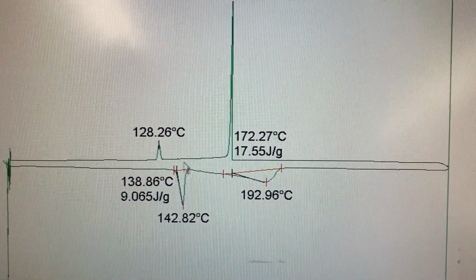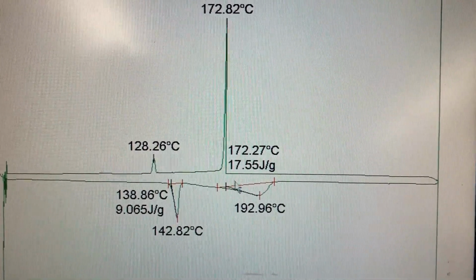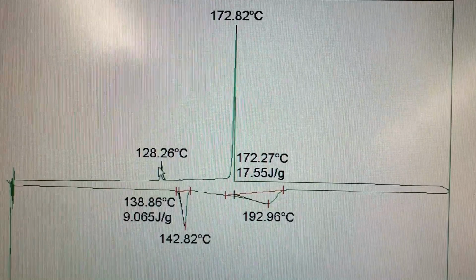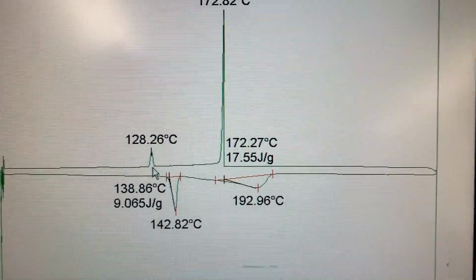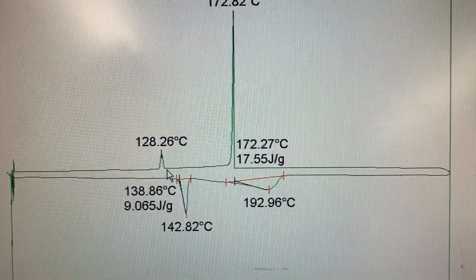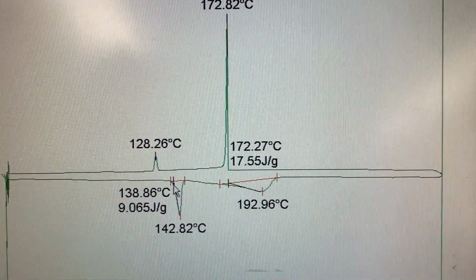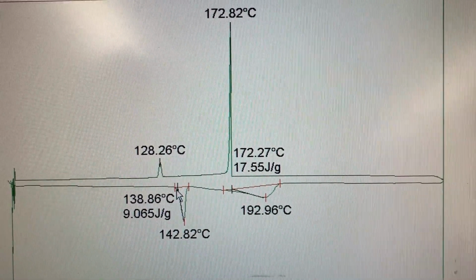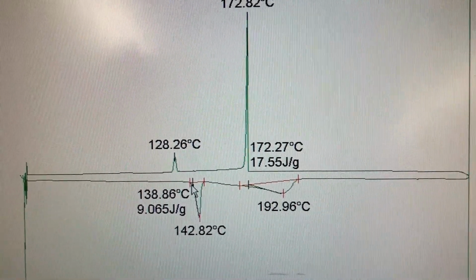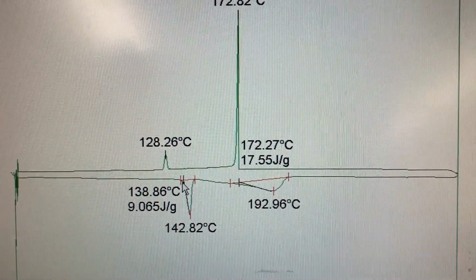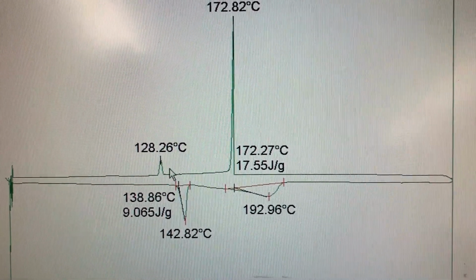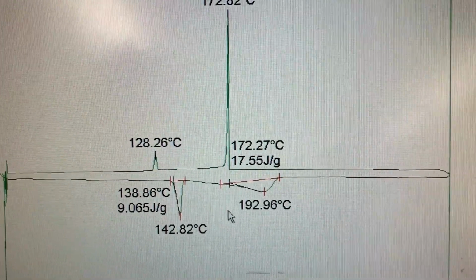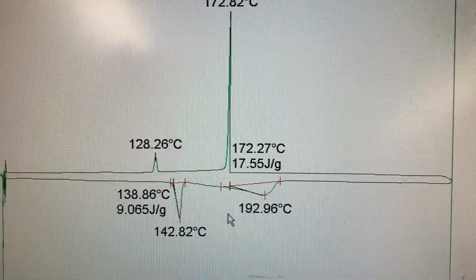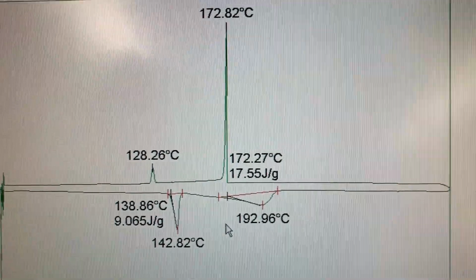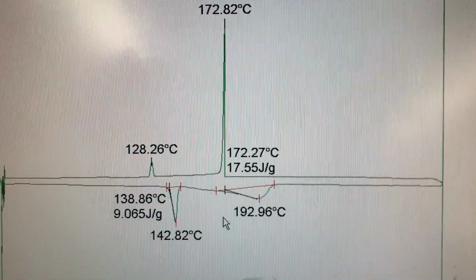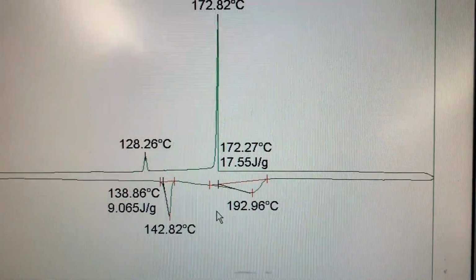And you can also notice how these peaks are kind of shifted. You can see how this peak corresponds to this melting and this solidification corresponds to this melting, and that the temperature at which it starts solidifying almost corresponds to the temperature at which it starts melting. As we talked about in the background, in the introduction part of the lab, the shift in the peaks is due to the dynamic effects of the heating and cooling rates that we're using. We're using 10 Celsius per minute, and if we were to use a much slower rate, then our peaks should have matched at the same temperature.